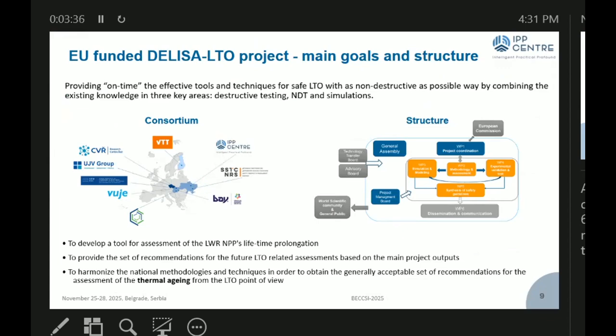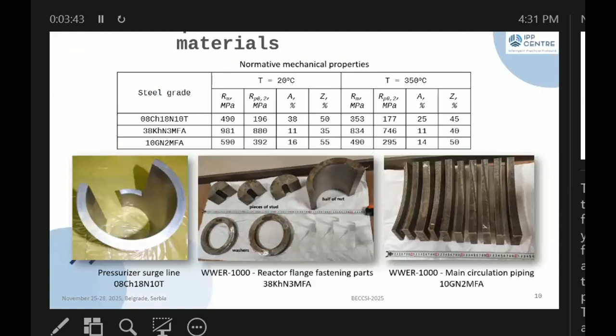Therefore, the main task of the LTO project is to investigate the thermal aging effect. To investigate these effects, 3 materials were selected for testing. The first is austenitic stainless steel cut from the pressurizer surge line after 28 years of operation. The second is ferritic steel cut from reactor flange fastening parts after 30 years of operation. And third, ferritic steel cut from main circulation piping in its initial state. The normative mechanical properties are shown in this slide.